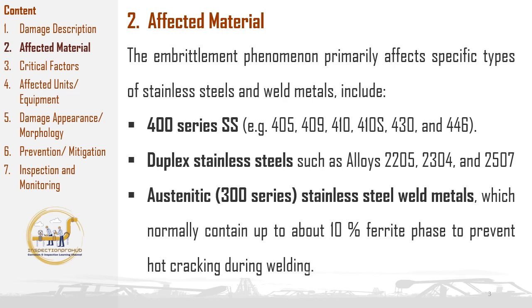Third is austenitic stainless steel weld metals in the 300 series. Austenitic stainless steels in the 300 series, such as 304 and 316, are commonly used in welded applications due to their excellent corrosion resistance, formability, and toughness. During welding, however, these alloys typically contain a small amount of ferrite, around 5 to 10%, in the weld metal to prevent hot cracking that can occur during solidification.